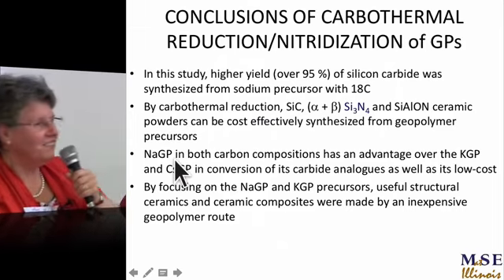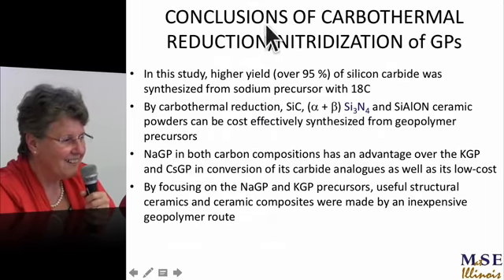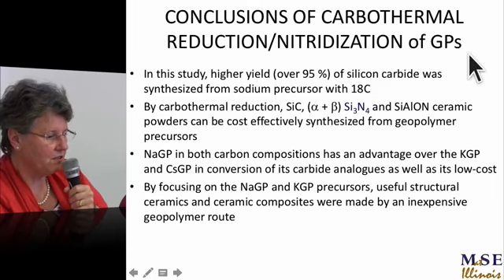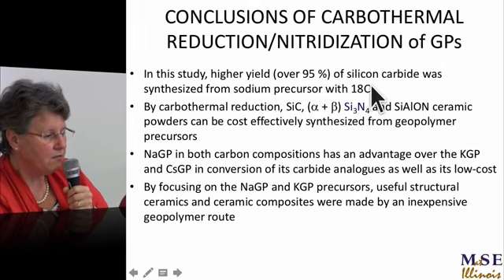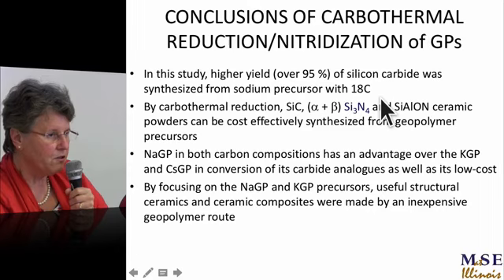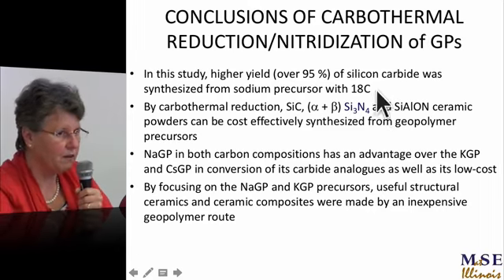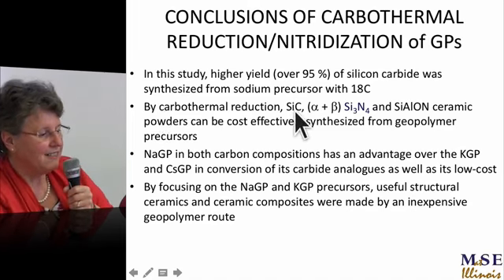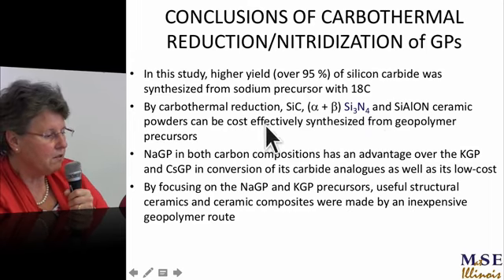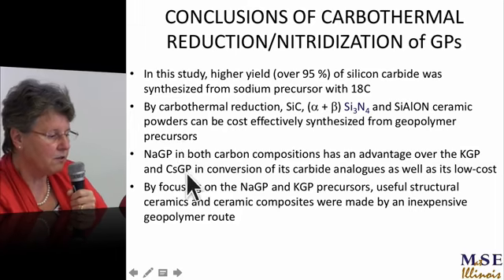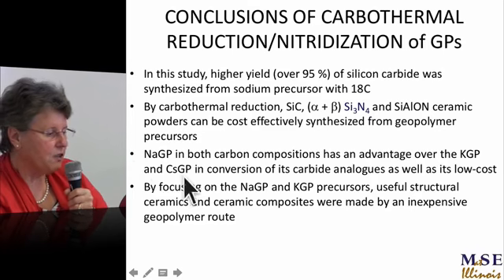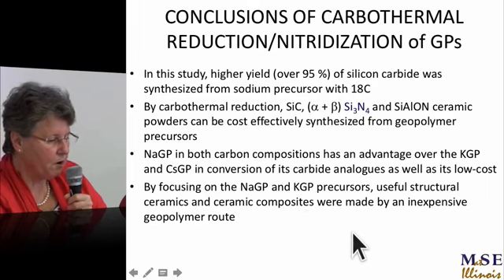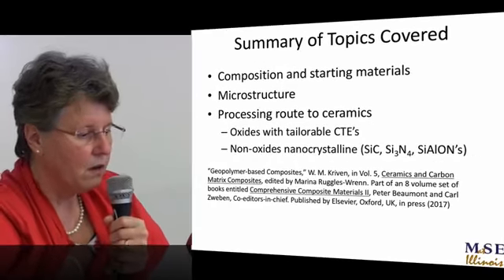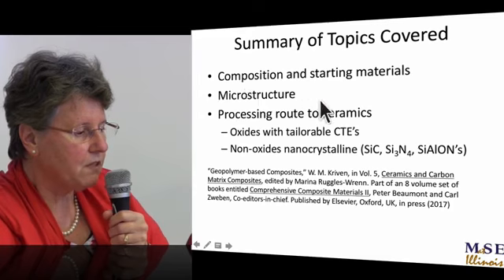So, in conclusion, this is the part where we wrap up. The carbothermal reduction or nitridization of geopolymers. Higher levels, over 95% of silicon carbide, were synthesized from sodium precursor using 18 moles of carbon, plenty of excess carbon to take away the oxygen. By carbothermal reduction, silicon carbide, alpha and beta silicon nitride and sialon ceramics could be cost effectively synthesized from geopolymer precursors. Sodium geopolymer has an advantage over potassium and cesium in its low cost. By focusing on the sodium and potassium, you can get useful structural ceramics and ceramic powders to make components by an inexpensive geopolymer route.